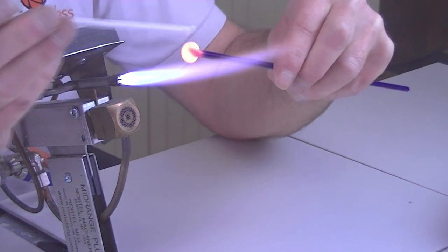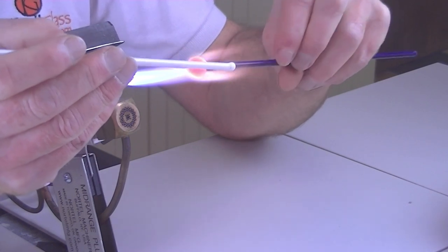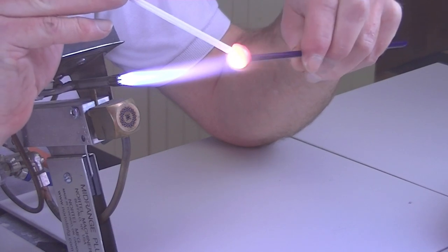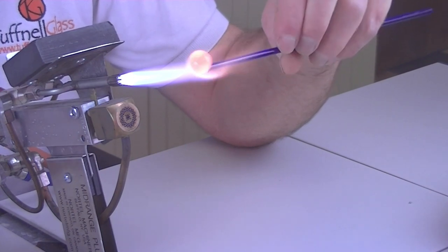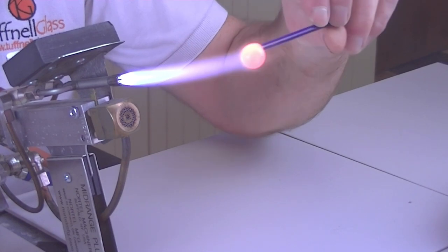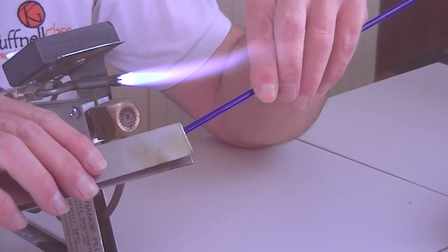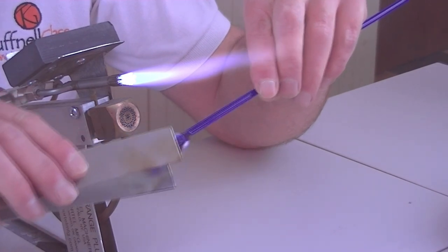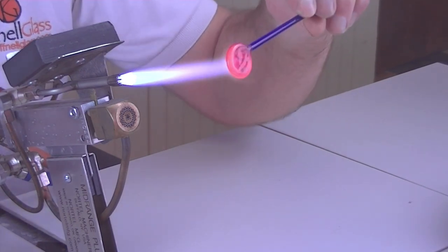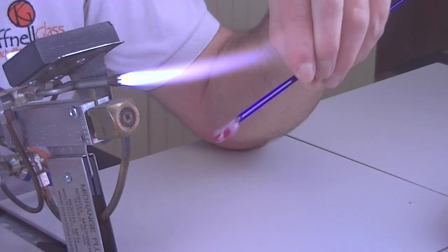I'm going to have a little pattern to this. I'm going to take some white glass and just start to pre-warm the white behind it, so hopefully we'll stop it cracking and shattering. But as we're just getting to the size of this bean size now, I want to wrap some white around it to form like a white marbling effect. And then I'm going to flatten this out. So if you imagine making like a little lollipop. Nice and round, nice and hot. I'm going to leave the flame with the mashers. Keep turning it until you've got it relatively stiff again. And then just flatten this out to the diameter of the rod, so it'll be like five millimetres thick. And don't forget just to flame polish either both sides where you've flattened it with your mashers. You're going to get little fingerprints where they've cooled rapidly. So polish those off, much better effect.